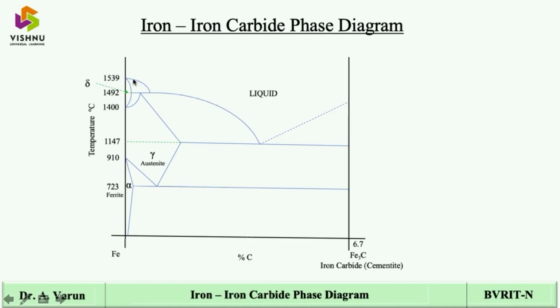Now it is very easy to mark the other phases, the two phase regions. On this side we have liquid, here we have delta, so this will become liquid plus delta. Similarly, here delta, here gamma, so in between you'll get delta plus gamma. Likewise, you have gamma plus liquid, and then L plus Fe3C, that is liquid plus Fe3C. So it is very easy to mark gamma plus alpha here. On either side, whatever phases are present, the two phase region will have that combination of phases.